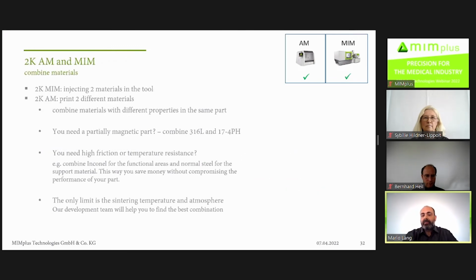2K AM and MIM combine materials. 2K MIM injects 2 materials into the tool. The same with AM: print 2 different materials, combining materials with different properties in the same parts. You have an application which requires magnetic and non-magnetic: combine 316 and 17-4 PH. You have an application where you need high friction or temperature resistance: combine Inconel on the functional area and cheaper normal steel for the support material.